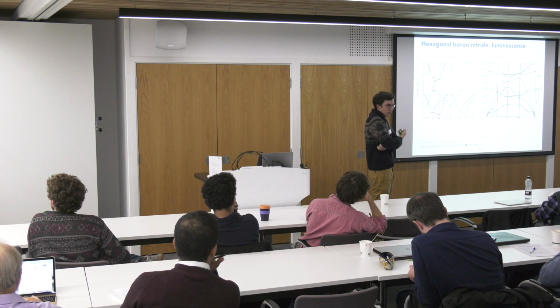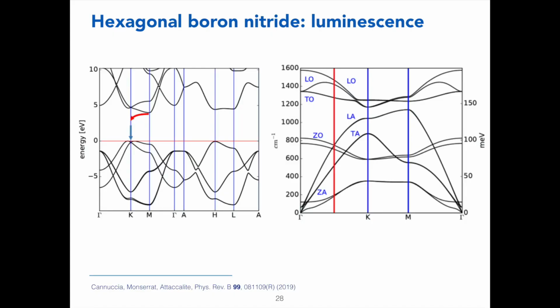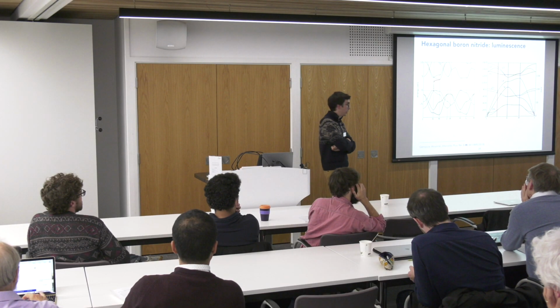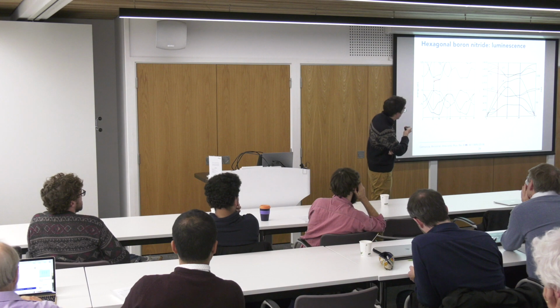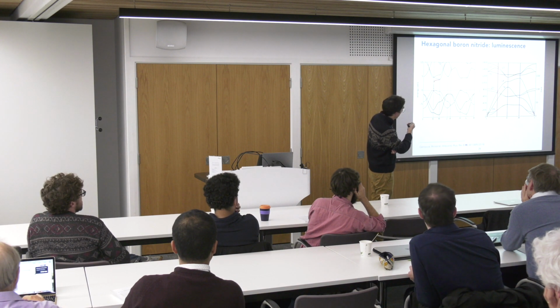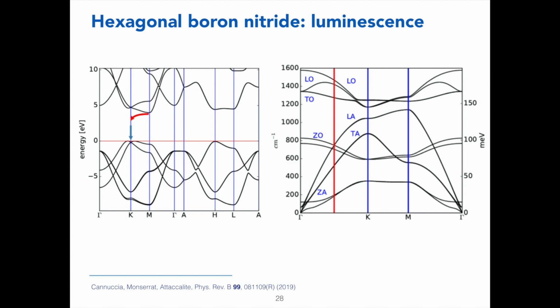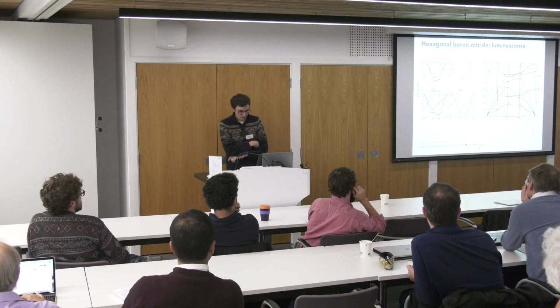And our hypothesis was, well, this is probably driven by some phonons that couple to the excitons and allow you to bridge this indirect gap here. So we calculated the phonon dispersion of this material, and we identified the phonon momentum, which is shown by this vertical red line, that has a momentum that exactly matches this difference between the K and the M points that would allow us to bridge this indirect excited state. I also want to point out that if you look at this particular phonon wave vector, you see that there are multiple energies of optical and acoustic longitudinal and transverse phonons.